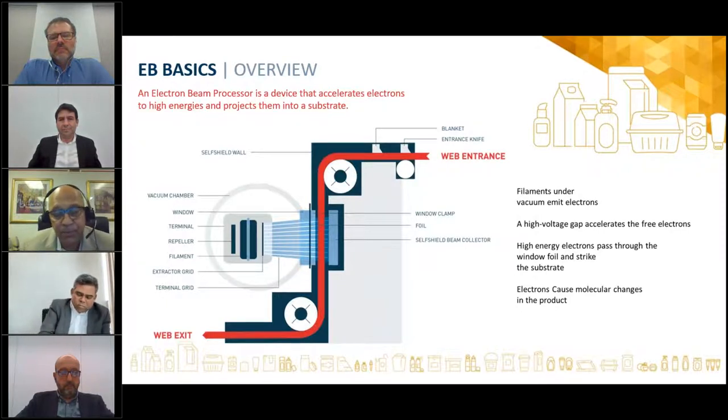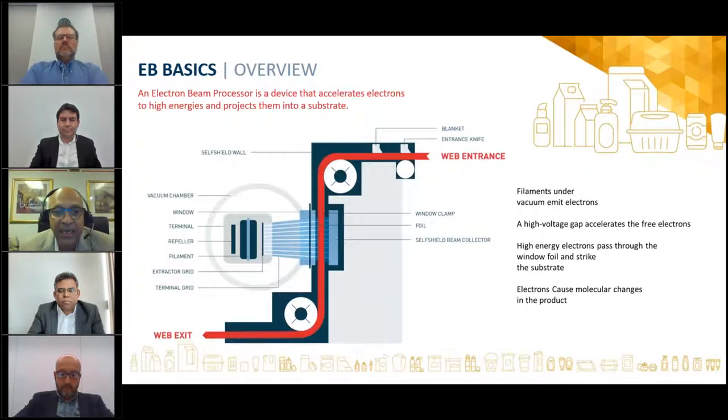Now the electrons are negatively charged, and when you apply a positive voltage, you extract the electrons from the tungsten filament and then accelerate them. They come out from the vacuum chamber through a very thin titanium foil, which is supported on a water-cooled copper body, and then into the process zone. The web is moving right here, and the web containing the EB ink, coating, or film, or whatever you're trying to cure, sees the electrons, and almost instantaneously, within milliseconds of reaction time,